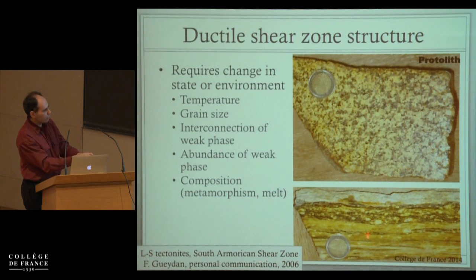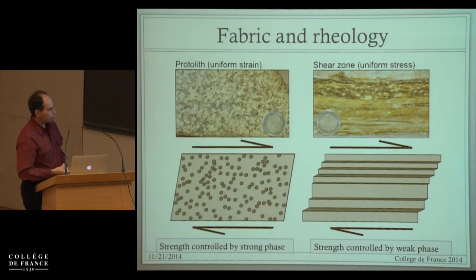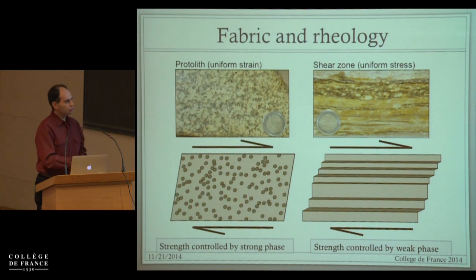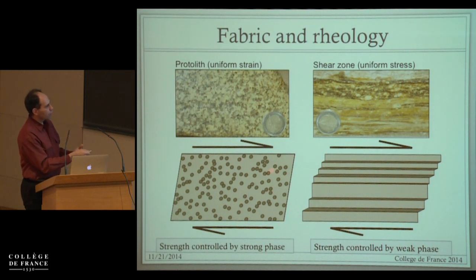The second is that you form these layers of the black stuff, which turns out to be the weaker minerals, and which seem to be fairly unconnected in the starting material. So we have evidence for reduction in grain size and formation of an interconnected network. We've been able to evaluate the importance of these various phenomena. For example, you compare the strength of an aggregate with a structure like this, with dispersed particles, to one in which instead you have layers of different material. This is much weaker. It's not a limit forever: the strength here will be controlled by the strong phase, and here by the weak phase.